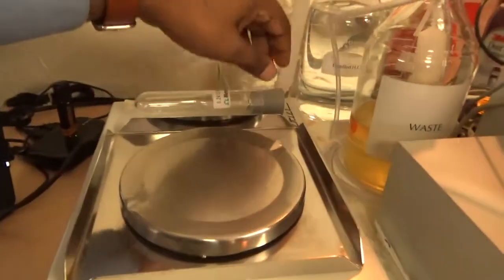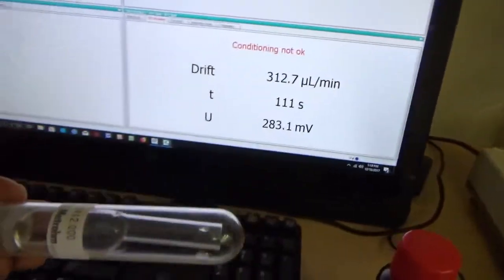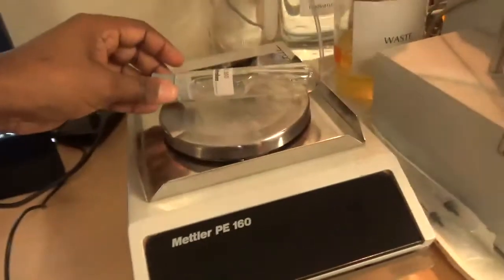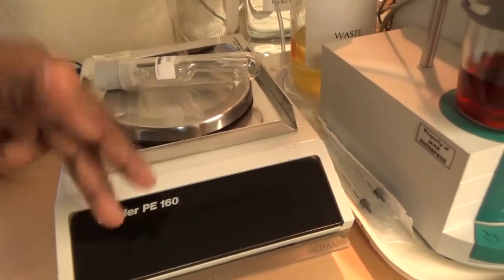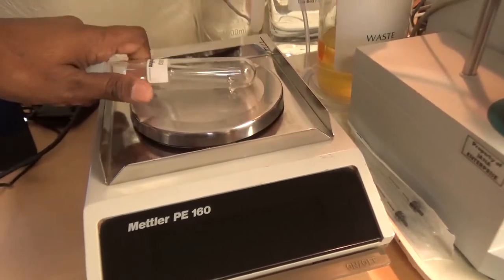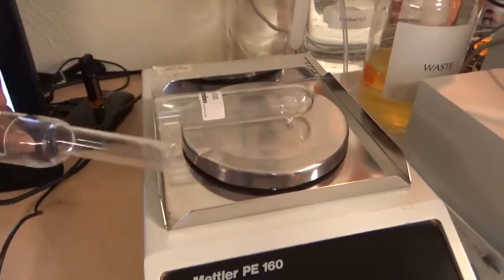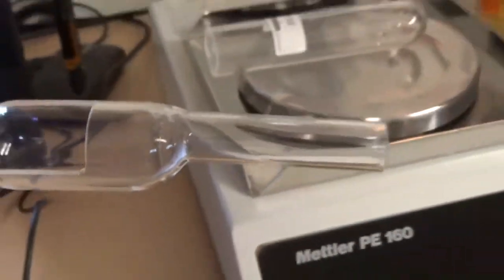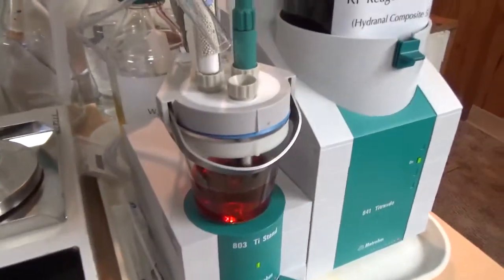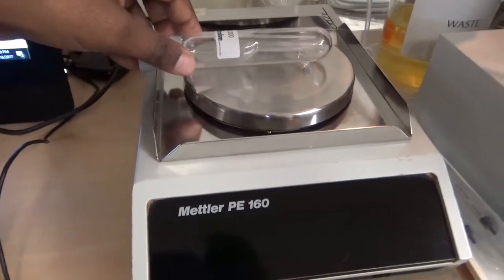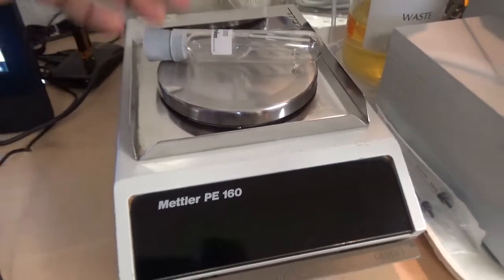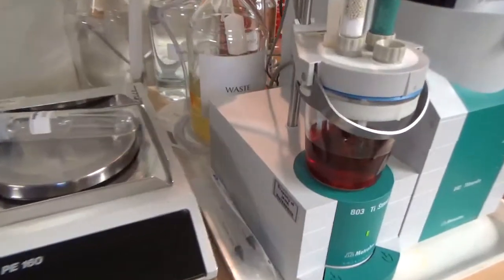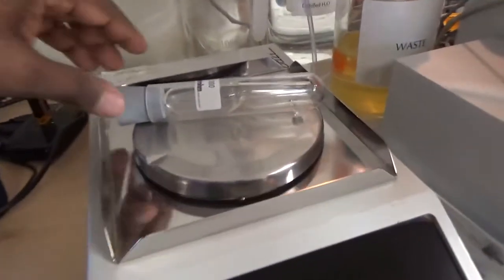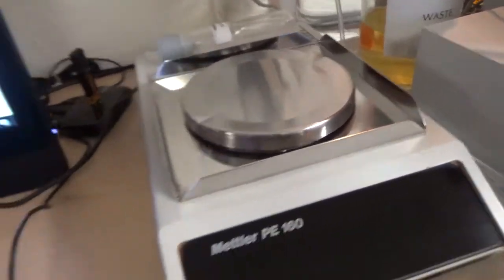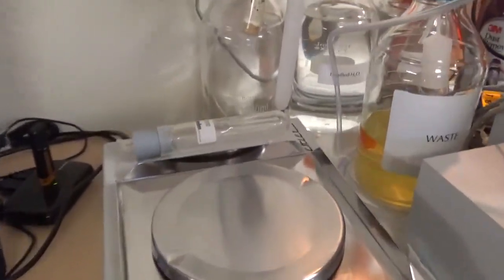We can also use the powder, and for powder we use this glass bowl. In this glass bowl we take the whole weight of the glass bowl with the sample in it, we tare it to zero. And then after we tare it to zero, then we remove this. The sample is actually in this bowl. When we do the powder sample, the sample goes in this bowl, and then we add the powder directly here, and then we insert this bowl again in the glass cylinder. We take the weight again. Difference between zero and the value is the amount of powder added, and that's how we determine the moisture content in the solid sample. Liquid sample we directly add with the syringe, solid sample we add with that bowl.